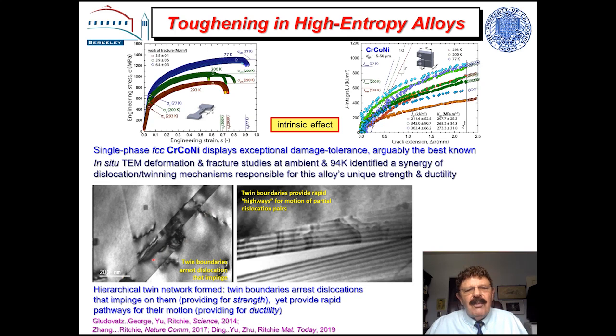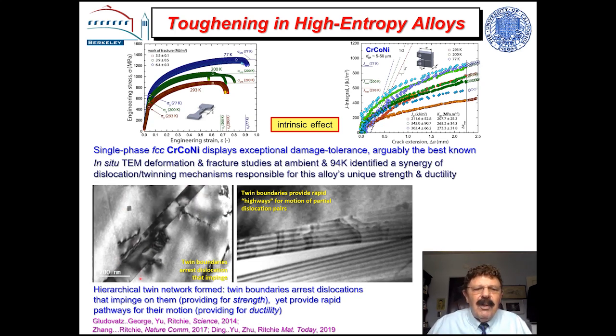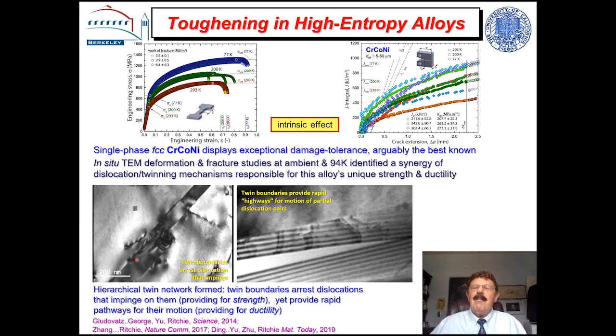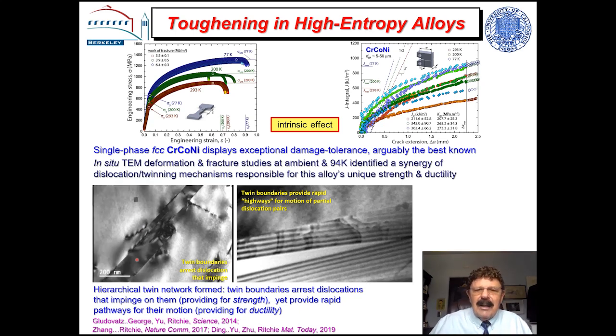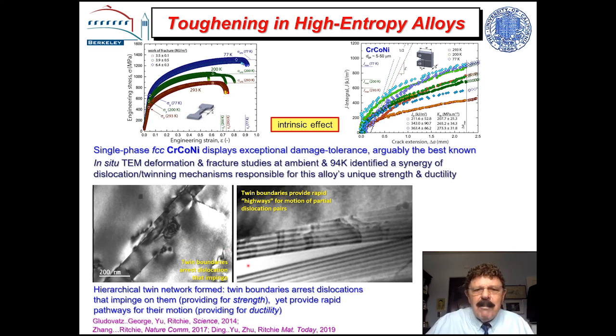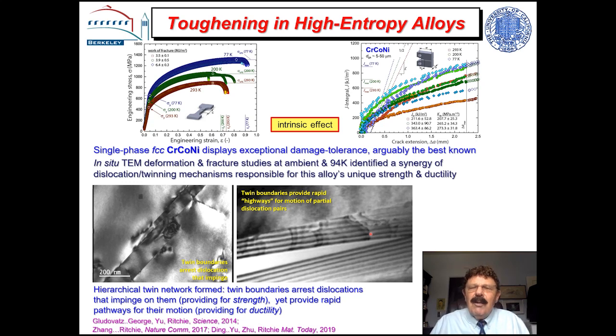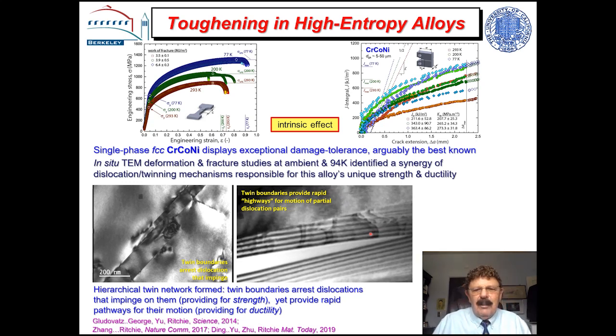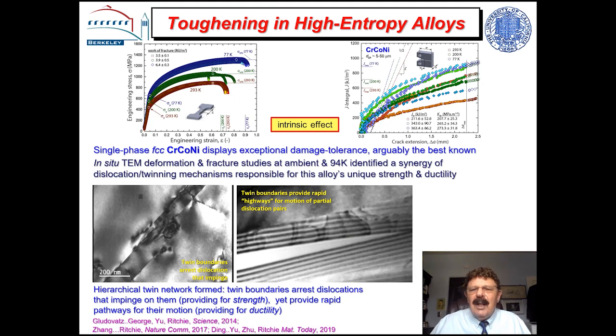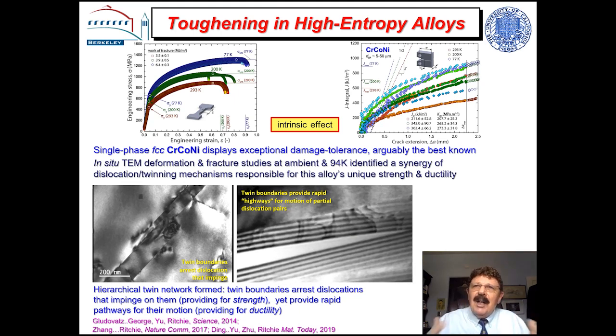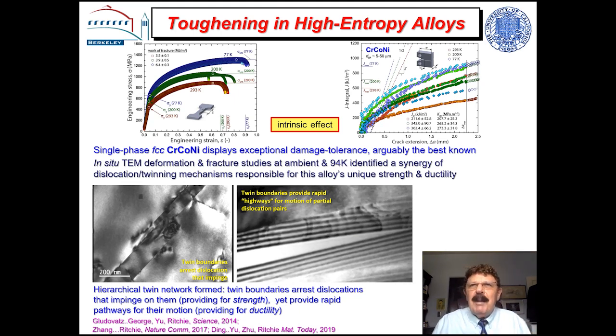This particular structure forms a hierarchical twin structure. The twin boundaries act to arrest dislocations that impinge on them. That is the hardening mechanism. But by the same token, these same boundaries actually act as highways for the dislocations to move. Those are the ductility mechanisms. So we have means of generating strength and ductility by separate deformation mechanisms, a synergy of deformation mechanisms to generate a duality of function, which leads to this very high strain hardening.